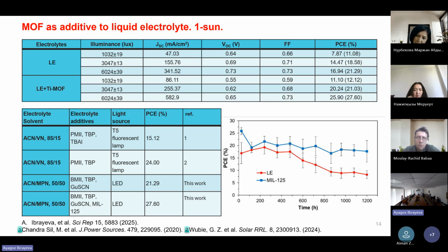And here you can see the photovoltaic performance of the fabricated devices under dim light, under LED lamp. It is 1,000, 3,000, 6,000 lux, and in all cases, quasi-solid electrolyte was higher than just liquid electrolyte. In the table, we collected other electrolytes and show that our prepared electrolytes work well. And for the stability test, we ran 50 days, and by the graphs we can see that we were able to improve the stability of these devices.